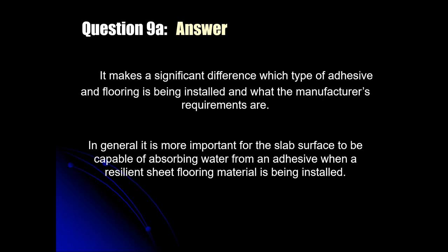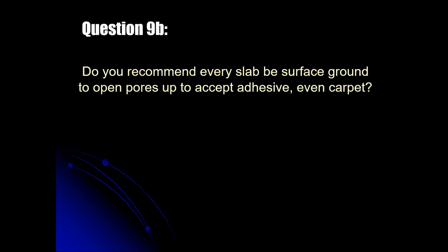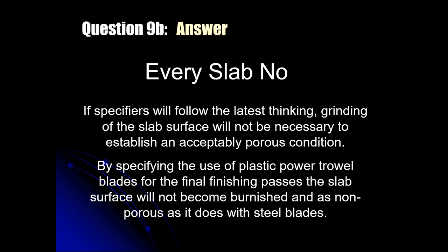Sheet goods require that you can't let the adhesive set anywhere near as long as you can with a dimensional tile installation. So they're often referred to as wet set or semi-wet set installations. And in those cases, if the surface of the slab does not readily absorb that excess water, several things can happen. And I'm going to show you in a minute what that can look like. So do I recommend that every slab surface be ground? Again, it depends. It absolutely depends. I don't recommend every slab. I mean, there are 100% solid epoxy adhesives and urethane adhesives that don't have water in them and don't require free water to be absorbed. So it really depends on what type of product you're going to be applying.